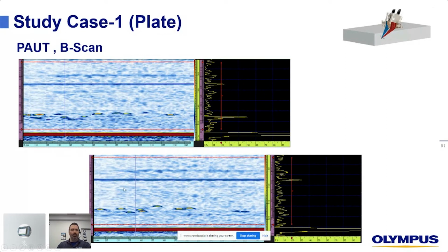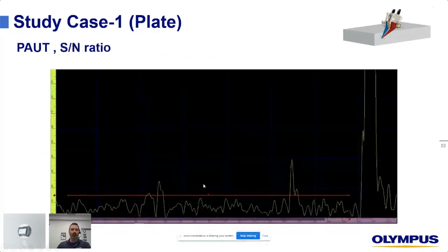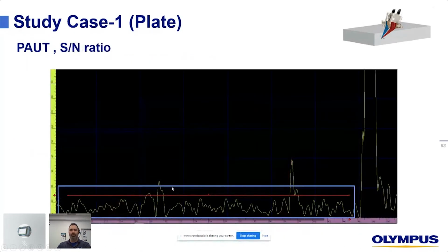But the overall signal or the overall noise is in the way. We talk about an average of 10 to 15% noise compared to a 40% high HTHA signal.